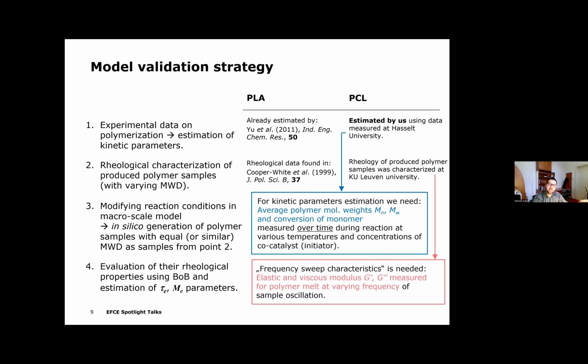For the PLA, we didn't have any experimental data from any collaboration or generated by ourselves. So the situation regarding the experimental data on polymerization itself was easy. As I already said, we took everything from the paper by Yu and co-workers from 2011. And for the rheological characterization, we had to find other data in the paper by Cooper, White and colleagues from 1999, who actually took 3 industrial samples of PLA with different molecular weight distributions and characterized the rheological properties of their melts. So this we did purely on the literature data.